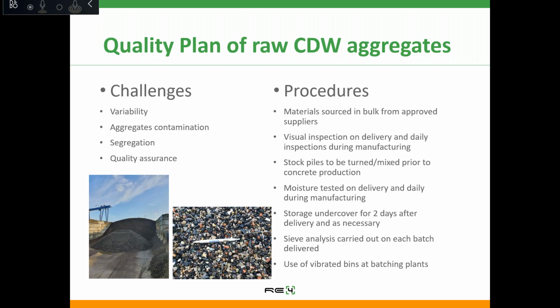Also, these aggregates are tested. We perform sieve analysis for each batch of material received, to make sure that the aggregates meet the supplier specification. Another thing that we know from experience when dealing with difficult sands, and we saw that with the CDW aggregates, is that the aggregates can segregate and stick in the bins when we are at the batching plants before going into the concrete manufacturing. So we only use vibrated bins to place the aggregates at the batching plant.